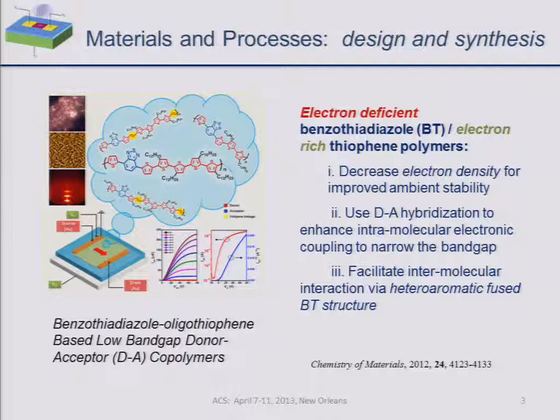Also, the donor-acceptor hybridization can narrow the band gap through intramolecular electronic coupling, and that can improve the absorption characteristics and therefore the efficiency of a device that would be using these materials. And then there could be improved intermolecular interactions because we have this heteroaromatic unit that's a fused structure in the middle, the benzothiadiazole unit in blue. We've done the synthesis of these materials, we've done a little bit of processing, and we've started to do some device characterization.